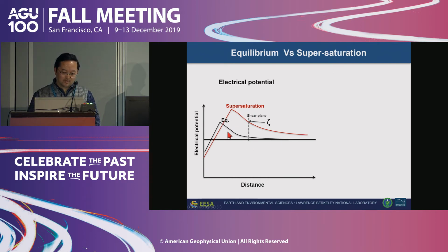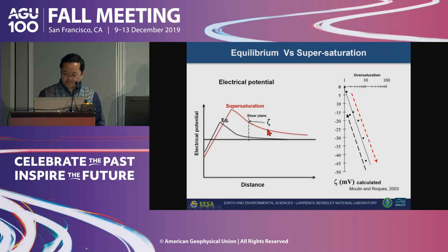So basically, in terms of the electrical potential, we can compare conceptually the equilibrium condition versus supersaturation condition. We have this heightened profile where, for example, the deposition on the shear plane is much enhanced. And again, there are data in the literature that show when you're moving away from equilibrium versus moving toward equilibrium, there's a potential change that is theoretically calculated.